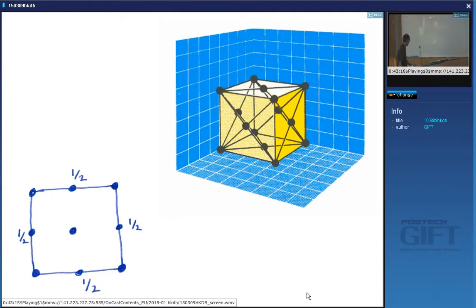So this is now a little bit more complicated. This is the face-centered cubic unit cell, where we have a lattice point at each corner and a lattice point at the center of each face. On the structure projection, it becomes very simple to look at. These are all at heights 0 and 1. So this is the face-centering lattice point on the face parallel to the bottom. Okay, you can see 0 and 1. These are located at coordinates half and half upwards. For example, this point here. And these are the face centers of the vertical faces, basically. So this is the structure projection of the face-centered cubic cell.